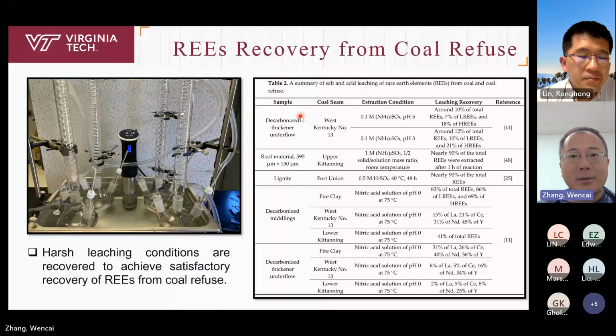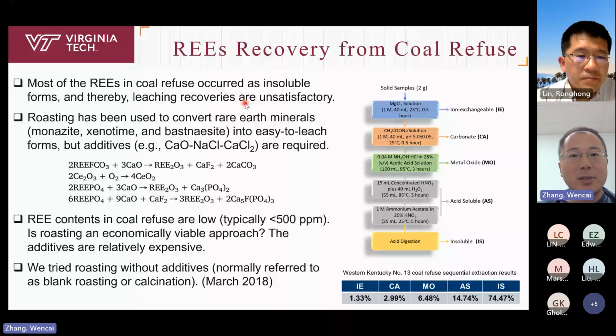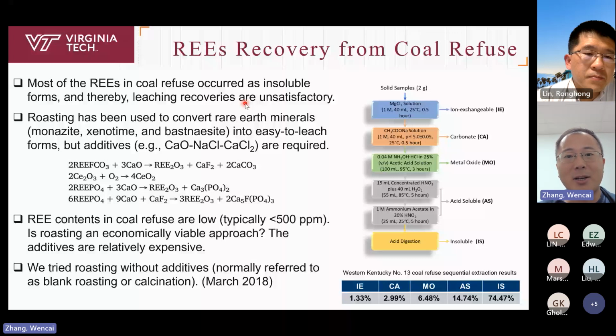So then we can go back to the major commercial resources of rare earths, which are ore deposits. For example, you have bastnasite, monazite, and xenotime. When people process these kinds of minerals, they normally use a technology we call roasting. It's easy to understand. You mix the minerals with additives such as calcium oxide, sodium chloride, and calcium chloride, and you roast this mixture at high temperature. In this case, the rare earth mineral will be converted to another chemical form, and this form will be much easier to leach compared with the original minerals. So this is roasting.